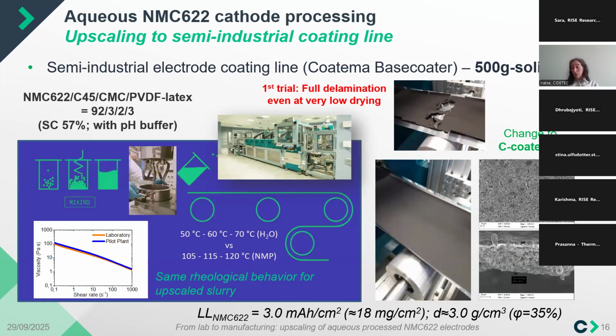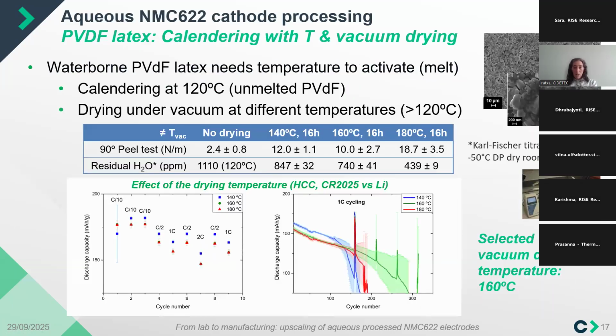When trying to improve energy density by going to higher and higher loadings in terms of areal capacity, this also leads to thicker electrodes, so all the drying steps—particularly speeds on the coating line and temperatures—have to be adjusted for each case.